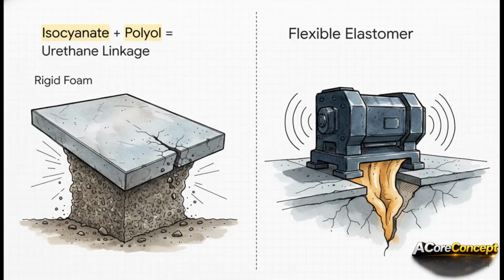The core performance of this grout is dictated by reacting an isocyanate group with a hydroxyl group, which is typically a polyol. Now, in heavy industrial settings, we're usually using aromatic isocyanates, like methylene diphenyl diisocyanate, or MDI for short. When you combine that MDI with lower molecular weight polyols, boom, you create this rigid, high-strength, closed-cell foam that is just perfect for lifting heavy concrete slabs. On the flip side, if you swap in high molecular weight polyols, you create a flexible, elastomeric polyurethane. And that flexibility is absolutely vital when you're injecting into dynamic cracks where you're expecting thermal expansion or heavy, continuous machine vibration.